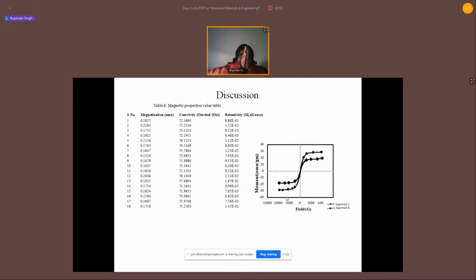For that attraction, what I am trying to do is print a sort of layer by layer tile, with the lower layer, which will be attached to the wall, having a high composition of Fe3O4. Then the next layer with, let us say, more composition of the wood. Then the next layer with the composition of PVC, and the top with PLA.